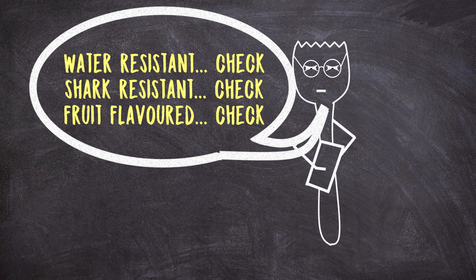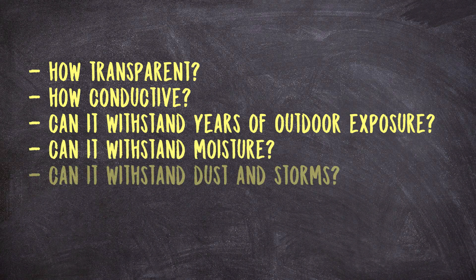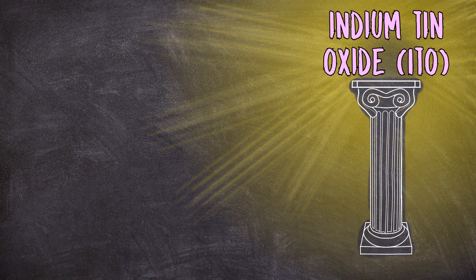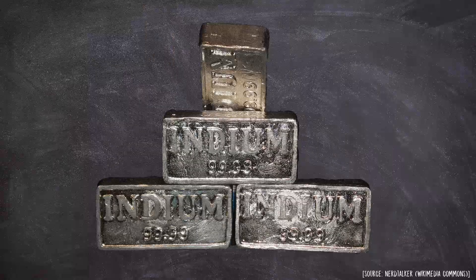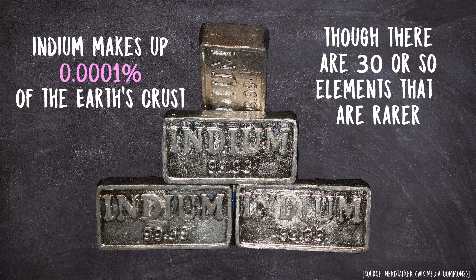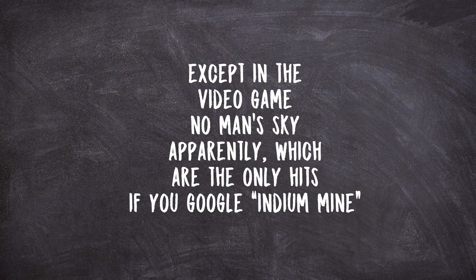And the final reason is that of the TCOs we know of, only one has really been found to tick a lot of the engineering boxes we need. There are a lot of design considerations. Sure a TCO is conductive but how conductive? How hardy is it? For example, a lot of TCOs are easily eroded by water or surface contact or decay over time, which makes them a poor fit for a lot of consumer applications. And for all these considerations the only TCO that has really taken off is indium tin oxide or ITO. Dollars to doughnuts you are looking through an ITO layer right now. And the thing is this — the I in ITO is a problem. I stands for indium which is a very very rare material. Strictly speaking it's not technically rare on our planet but it doesn't just show up in our crust with big deposits we can mine.